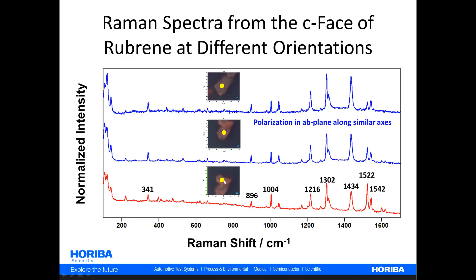Now we look at a single grain, probably in the same crystal orientation, except rotated 90 degrees with respect to the others. Now we see differences in the relative intensities of these Raman bands, particularly at 1004 wavenumbers, compared to the bands at 1302, 1434, and 1522. Notice the difference just by rotating the crystal 90 degrees — this shows how, even for a single grain, Raman spectroscopy with incident polarized light is very sensitive to the orientation of the crystal.